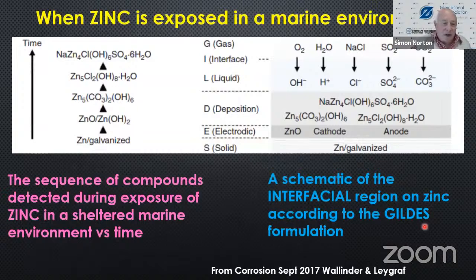This is some of the latest work that's been done on the exposure of zinc in an atmosphere, in a marine environment. And if you look on the left, you'll see all the compounds that form when zinc is in a sheltered marine environment over time. So there's your galvanized steel structure or your galvanized bolt.